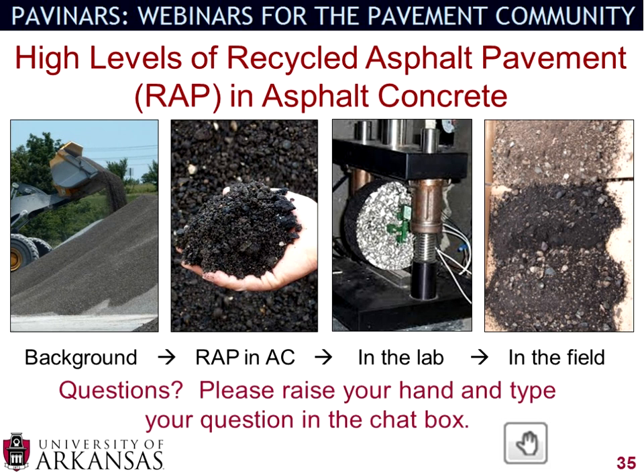And what's important to do with this, though, is to go back to your proper sampling technique and proper evaluation technique. So if you're sampling that material and you know there's a high level of crack sealant material in there, you want to make sure that you are taking some of that crack sealing material and trying to get the proper ratio of crack sealing material to overall RAP material. Then as you run those extractions, that crack sealant and the properties of that crack sealant will get pulled out with the RAP material. So I think that with enough crack seal material, or really enough of any sort of pavement maintenance or pavement rehabilitation product, you can see that influence the RAP material.